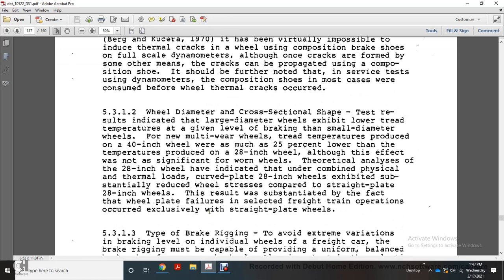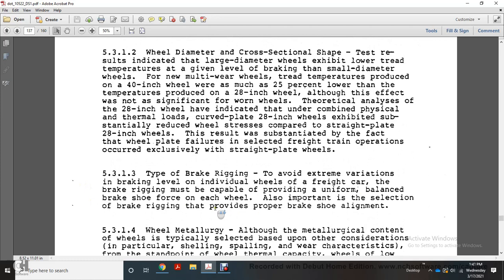Wheel diameter and cross-sectional shape. The test results indicated that large diameter wheels exhibit a lower tread temperature for a given level of braking than small diameter wheels. New multi-wheel tread temperatures produced within a 40-inch wheel were as much as 25% lower than temperatures produced in a 28-inch wheel, although the effect was not significant. The theoretical analysis for the 28-inch wheel would indicate that the combined physical and thermal load with the curved plate in the 28-inch wheel exhibited a substantially reduced wheel stresses compared with the straight-plate 28-inch wheel. The result was substantiated by the fact that wheel plate failures in selected freight train operation occurred exclusively with the straight-plate wheels.